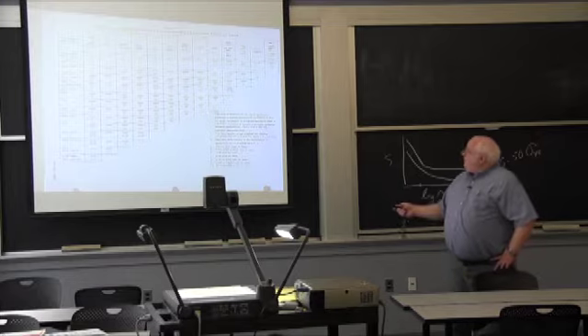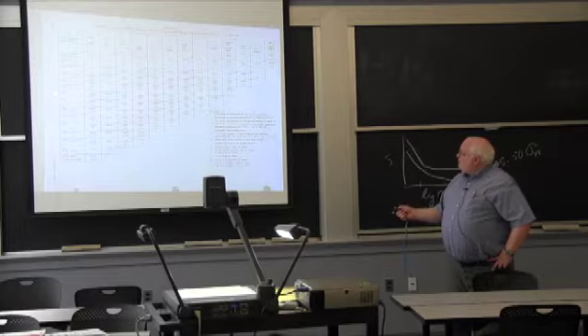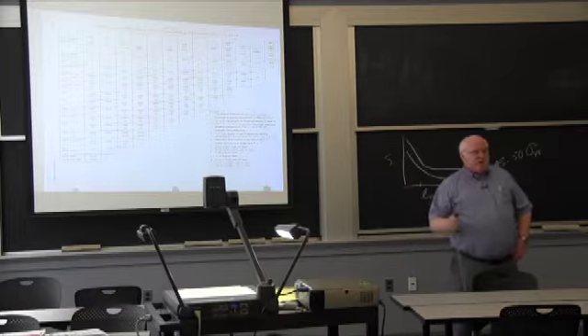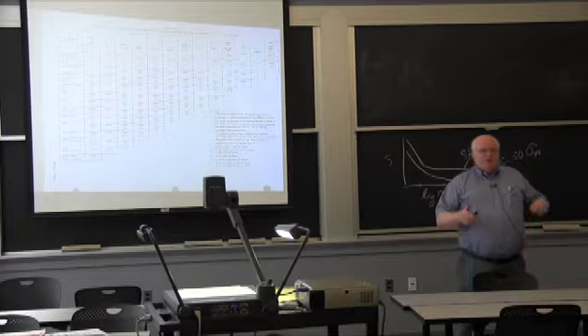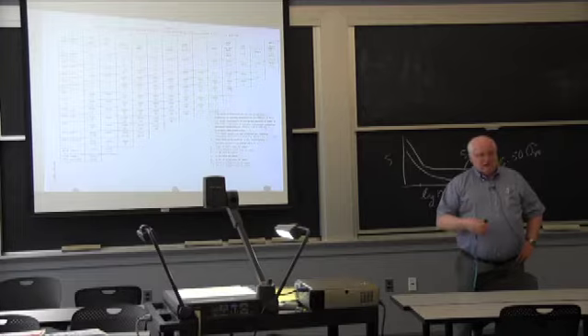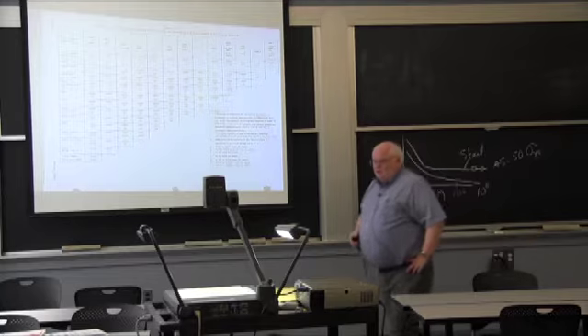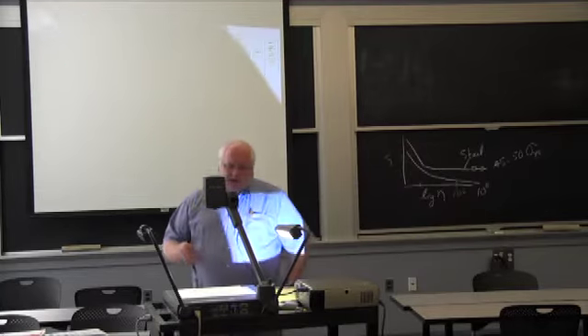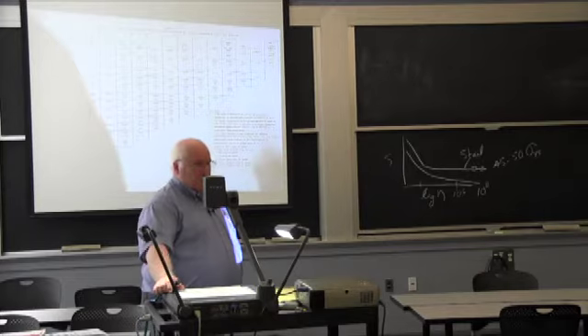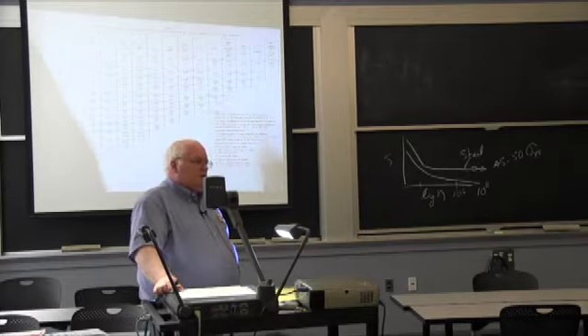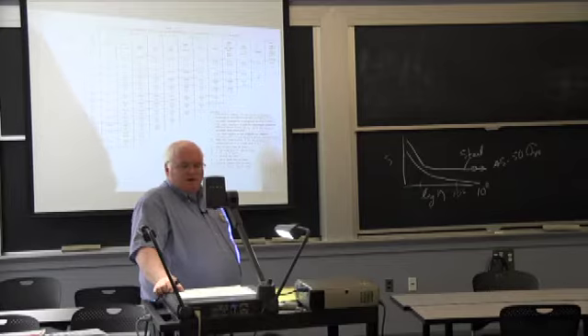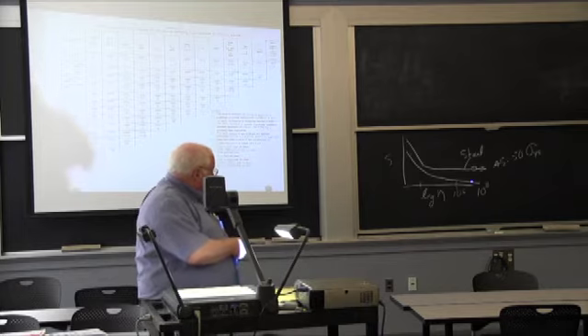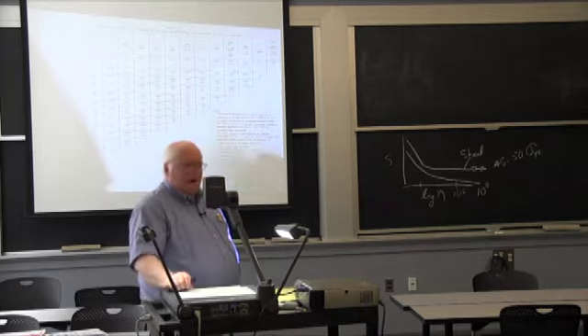Okay? So in fact, what they typically use for welding of ships and things are 5000 series. The problem with those is they've only got 20 or 30 KSI yield strength. Well, that's significantly less than something like an HY100, which is what you build a submarine out of today, which is 100 KSI, right? So it's got 1/4 the strength of a submarine steel. It's got about half the strength of the plate on a surface ship, okay? So aluminum doesn't have the yield strength, it doesn't have the fatigue strength, and you have to be very careful about what filler metal you use.